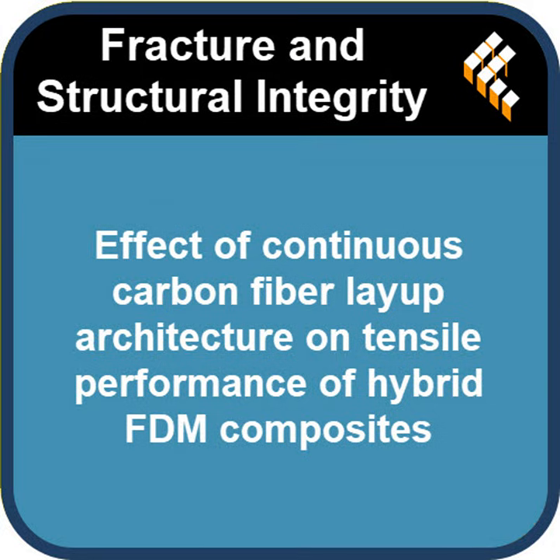Precisely. The researchers found that off-axis layers, those 30 or 60-degree prints, prevent the plastic from failing under shear stress. The angled layers essentially create a maze for the stress forces. So instead of a crack shooting straight through the plastic, it hits an angled fiber and gets deflected. Right. In engineering terms, it creates a mixed mode 1 and mode 2 failure, which basically stops the part from just abruptly shattering. Okay, so we need 0 degrees for pure pulling strength, but we need those off-axis angles, almost like plywood, to stop cracks from spreading.